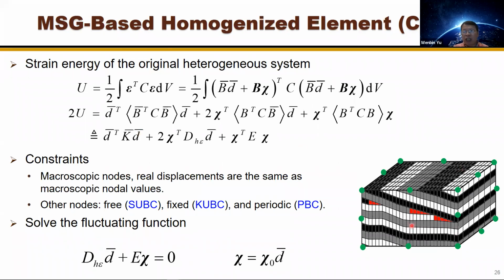And then for the surface element, how these nodes are not captured in the global analysis, there are several ways to apply it. It depends on your situation. If it's stress free, then we should let it free if it's a free surface. If it's connected with another surface, we need to use a so-called periodic boundary condition, in such a way that we allow it to vary in a certain fashion. And in terms of the nodal global nodes and also shape functions, you have another additional flexibility there.